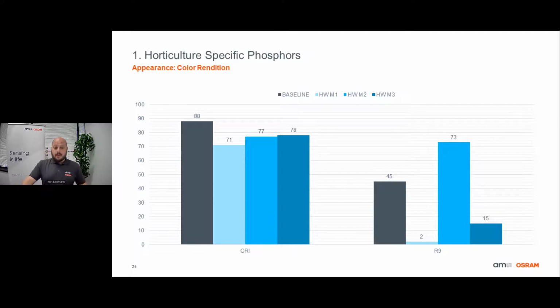So what about color rendition? While not a horticulture specific metric, it's still somewhat important for crop inspection, right? So the CRI value for the three Horti white solutions is slightly lower than that of the baseline. However, they're all still above 70 CRI. The M2 and M3 are actually quite close to 80 CRI. Things do get a bit more interesting when we look at the R9 value.